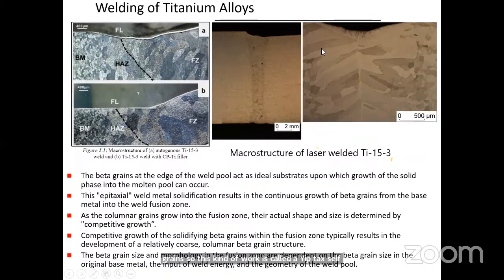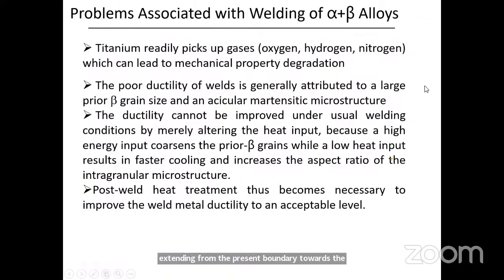And because of the high thermal gradient present in laser welds, you can see coarse columnar grains extending from the fusion boundary towards the weld center. I already mentioned the interstitial elements like oxygen, hydrogen, and nitrogen. If they are present in the weld metal, they degrade the mechanical properties. Poor ductility is mainly associated with large prior beta grains and acicular martensite. If any martensitic microstructure is present in the weld metal, strength will increase, but ductility will drastically decrease.